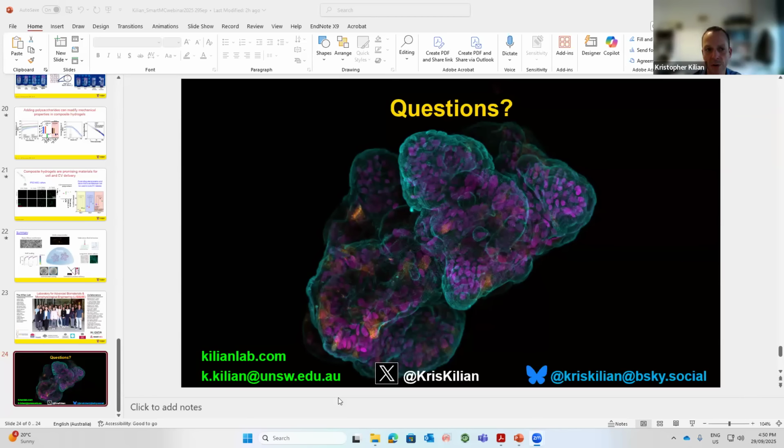And they're in 3D in all of the alginate and gel and gum cases that I showed. And so they really like 3D, and it'll certainly affect how they behave in vivo. I mean, we find the cells can move through the material. They don't travel too much from what we've seen. But at the low weight content, the 0.5 weight percent, they certainly spread out and move and migrate around.